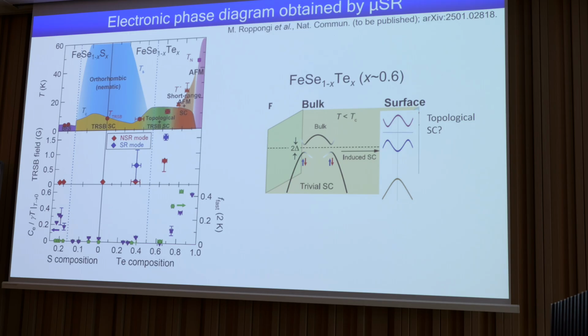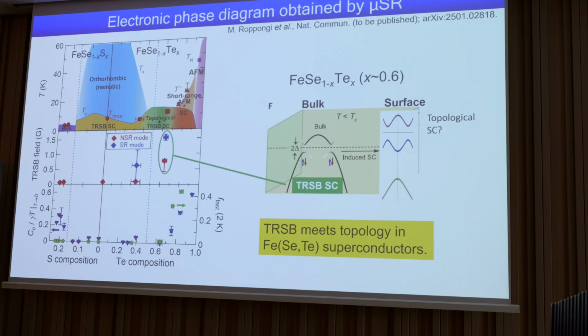However, our measurements with muSR detect this deep in the bulk. This indicates that we actually have time reversal symmetry breaking superconducting states deep in the bulk, which affects the surface states and creates a Dirac gap.